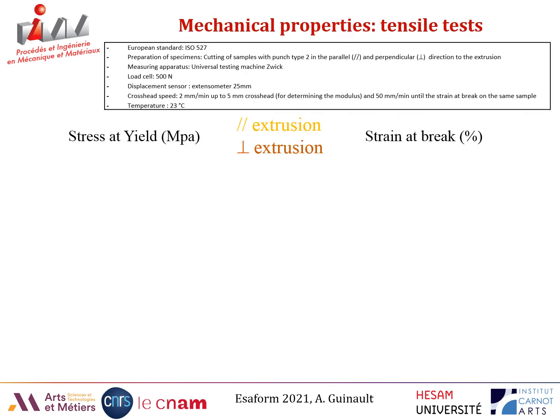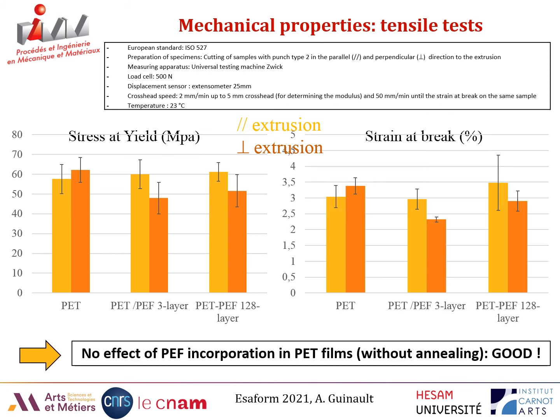About the mechanical properties, and especially the tensile test without annealing, we have measured the stress, the modulus, the stress at yield, the strain at yield, the stress at break, and the strain at break. Here I show you the stress at yield and the strain at break in the parallel direction to extrusion and perpendicular direction to extrusion. And so what you can see on the two graphs is that finally we don't have any effect of PEF incorporation in PET films without annealing, and whatever the number of layers. So it means that you can incorporate PEF that is brittle, but it doesn't bring a decrease of the mechanical properties. That is good.